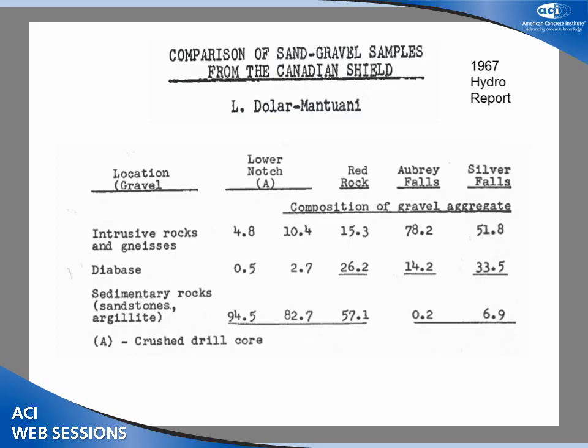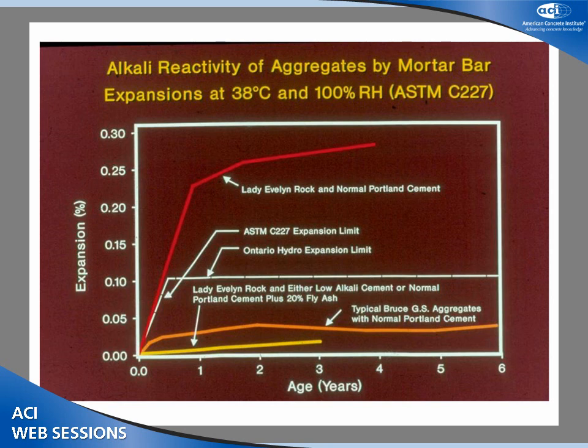This is just some information on the rock types, not really important. But they identified these reactive phases in the rock types that were used. And that's the original 227 data, showing that if you made it with high alkali or normal Portland cement and this rock material with a dam nearby that was built at a similar time, then they would get deleterious expansions. They could either use fly ash or low alkali cement to control that.